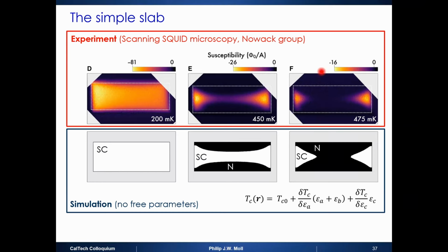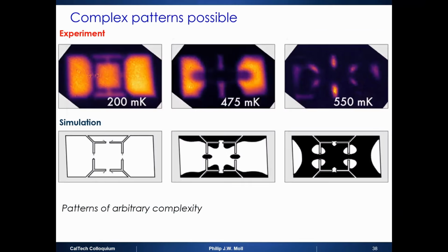So what happens here is that you essentially have two stabilized superconducting banks that are connected with this very weak superconducting wire, if you want, that you then separate at a little bit higher temperature. So you can play with, for example, Josephson type couplings within an SNS type setting within the same single crystal without a junction. So this is one of the main goals. We're still working on this to build junctionless Josephson junctions.